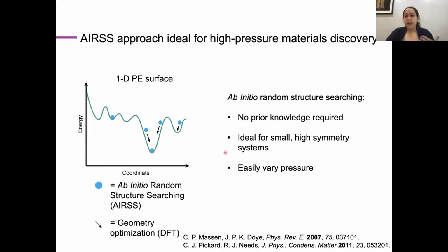However, that said, we like to start off by imposing sensible biases to our search to ensure sufficient sampling. And so we start off by sticking to relatively small unit cells, introduce some symmetry elements, as well as density constraints. Sort of at a practical level, to encourage you to use this very implementable approach, it's quite easy to include pressure in your calculation. It is simply a variable you set that is included in your enthalpy calculation that goes into the geometry optimization step.